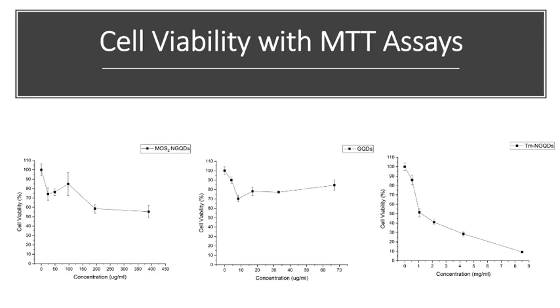What we're looking for here is 80% viable cells or more. Cell viability is how many of them are alive, and we're looking for 80% because that's the standard in the research that we're doing. Here we had to do 6 serial dilutions on each of these 2 samples, the graphene quantum dots and the thulium NGQDs. The molybdenum disulfide, I mentioned earlier, was hard to dissolve in water.